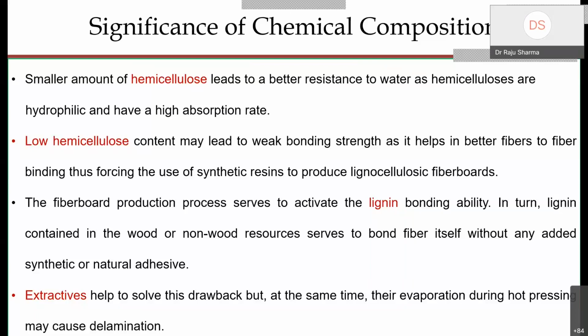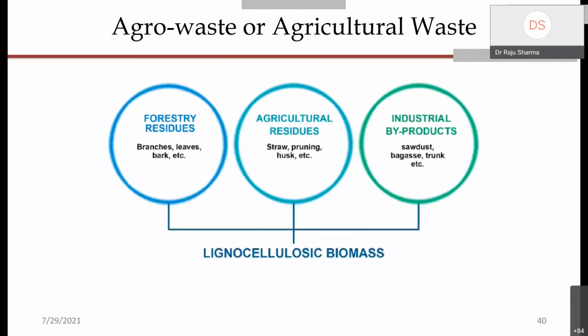Low hemicellulose content may lead to weak bonding strength. So those kinds of fibers which have a low hemicellulose, they will be limiting the durability of the product. The fiberboard production process serves to activate the lignin bonding ability. In turn, lignin contained in the wood or non-wood resources serves to bond the fiber itself without any added synthetic or natural adhesive, right? Extractives help to solve this drawback, but at the same time, their evaporation during hot pressing may cause delamination. So there are limitations also with this.